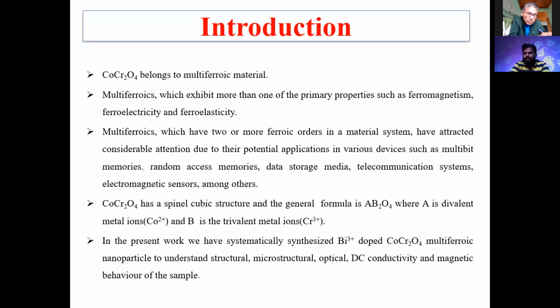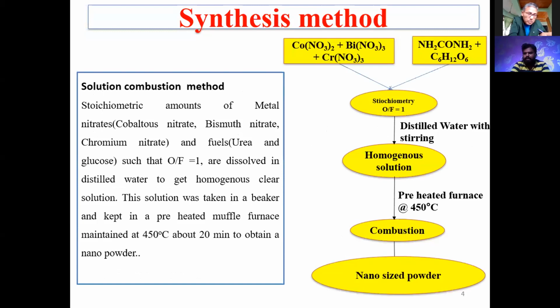The flowchart of the solution combustion method. In the solution combustion method, stoichiometric amounts of metal nitrates such as cobalt nitrate, bismuth nitrate, and chromium nitrate, and fuels are taken. We have taken a mixture of fuels, that is urea and glucose. The oxidizer to fuel ratio is 1, based on the valence of the oxidizers and fuels. This stoichiometric amount of solution was diluted with double distilled water, and this solution was mixed on a magnetic stirrer for 1 hour to get a homogeneous solution.